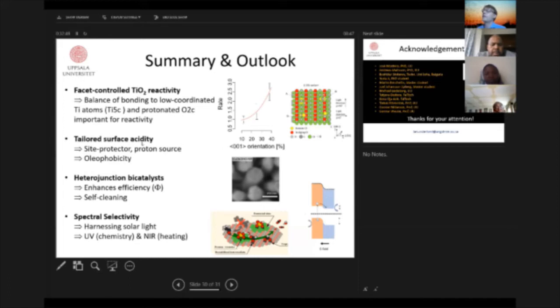We can tailor the surface acidity, have a site protector and proton source with some really interesting properties. We can do this heterojunction photocatalyst, where it can help to avoid or reduce the electron-hole pair recombination, which is one of the reasons that, for example, titanium dioxide is quite a poorly efficient catalyst. And this is the example of these nanorods covered with copper oxide. And then if you use solar light, you can actually exploit more of the light source and enhance the catalysis by heating one part of the system and doing chemistry on another part of the system.